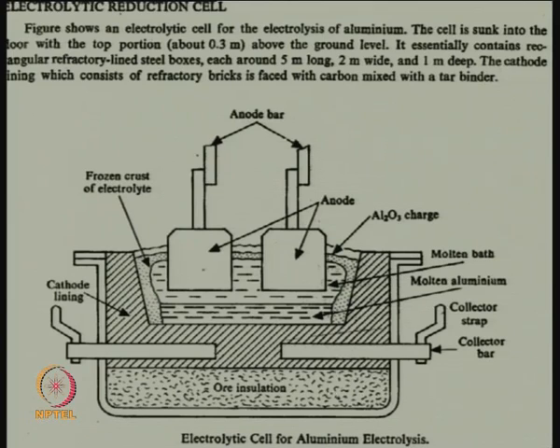Here I show schematically an electrolytic cell. This is the electrolyte, which has Al2O3 dissolved in cryolite. Alumina is continuously charged here, and there is a frozen crust of electrolyte all around, and this floats on top of aluminum that is continuously produced. Anodes are two graphite blocks.